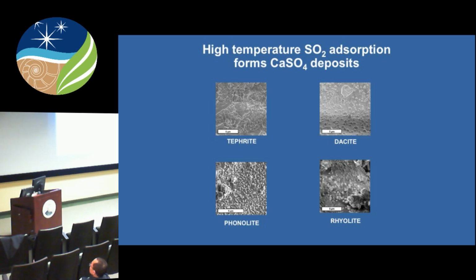And then, of course, there's the growth of crystalline phases on the surface of the particles, which these are examples of, where you see, for example, the anhydrite growing on it, and then you have the classic reactive growth scenario where you have to try to calculate the transfer through a growing impediment or a growing barrier, like in metamorphic petrology, classic literature. And it depends a little bit on chemistry, which is, of course, what we're trying to argue here. We're still the petrologists on the inside. Chemistry counts. And alkali to calcium ratio counts a lot in the rock.